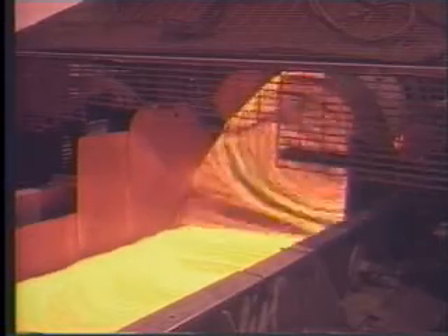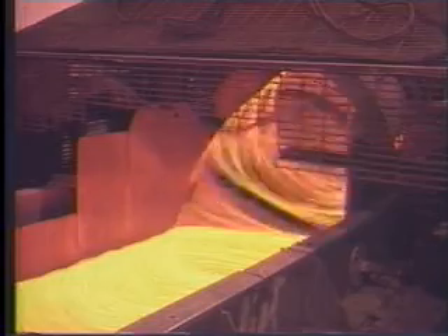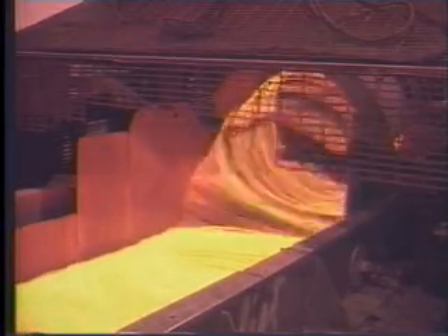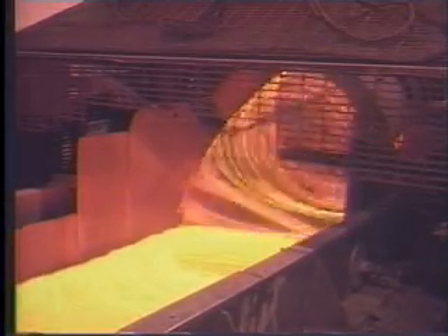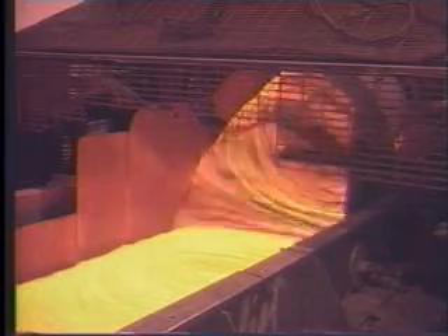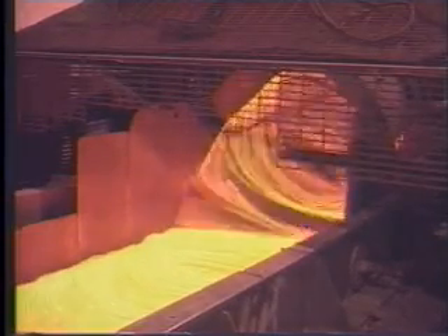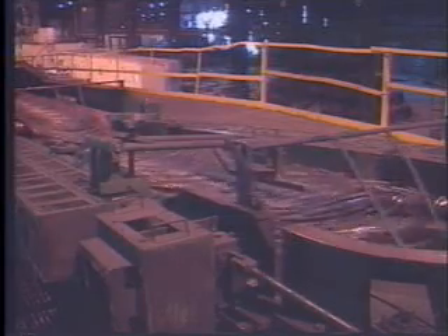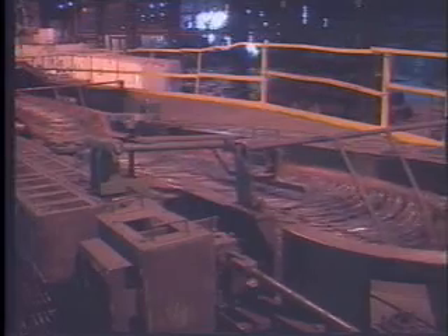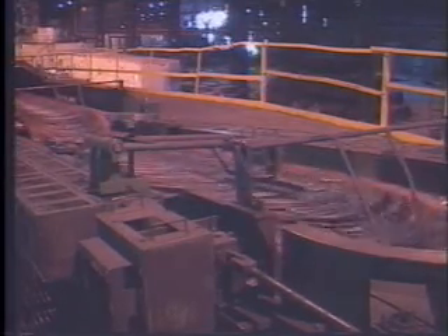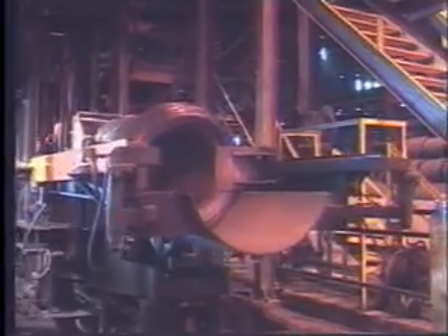Following reduction to final size, the rod is processed through a laying head. The laying head imparts a circular shape to the rod and allows it to cascade onto a moving roller conveyor. The roller conveyor allows for the controlled cooling of the steel rod. The laying temperature and cooling rate, coupled with the original chemistry of the material, will dictate the physical properties of the rod. The rod is then accumulated into a coil form in the reform tub.